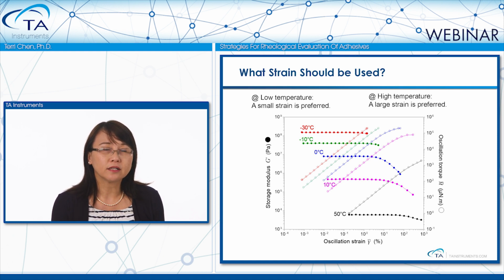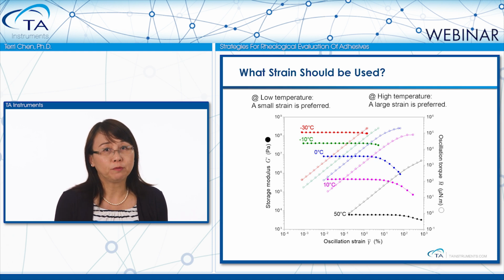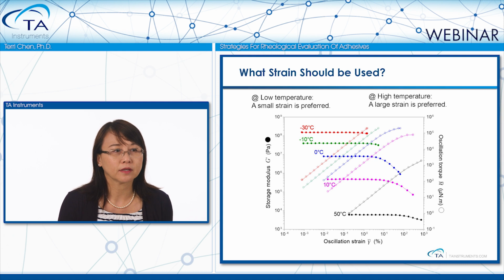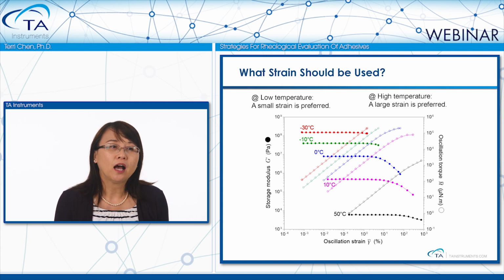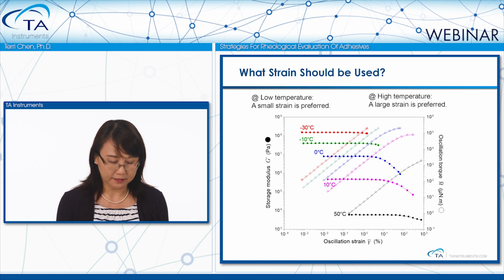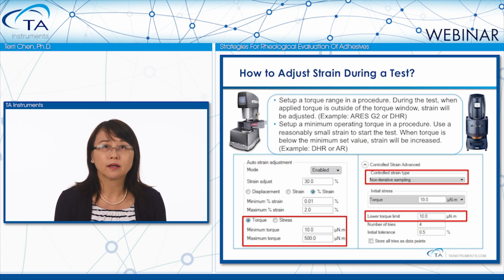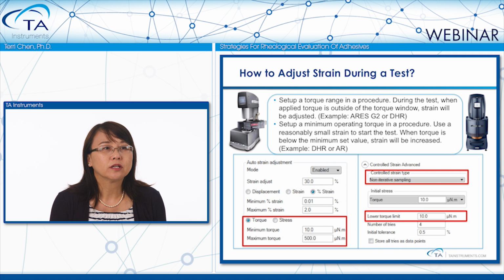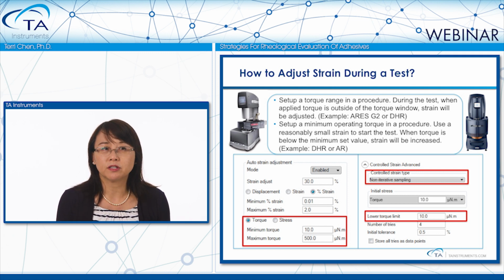So in this case, using a large strain will be preferred because small strains will result in some noisy data if your instrument is not on a perfect anti-vibration bench. Then the question is, how do we change the strain in the middle of a temperature ramp experiment? Different rheometers and different software use different methods to alter the measurement strain in the middle of a test.